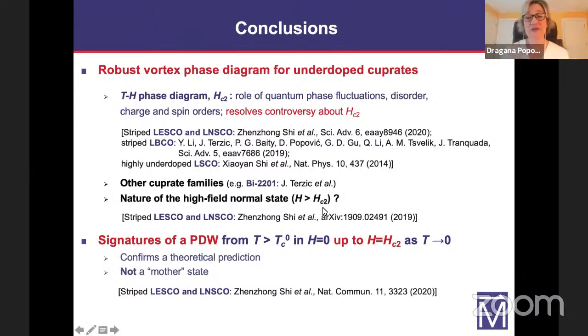So, in the high field normal state, what we found, first of all, for the temperature dependence of the in-plane resistivity, is that it is insulating-like, most likely a logarithmic temperature dependence, similar to what had been observed very early on in LSCO by Ando and Boebinger. What is different here is that as we keep increasing the field, this weak insulating-like dependence is actually suppressed. And it seems that the high field normal state is a metal, and this is described in this first paper here.